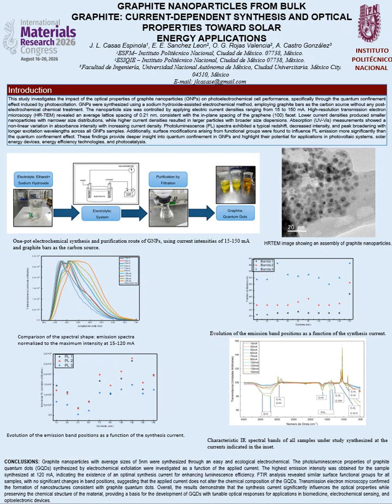In particular, the increase in nanoparticle size up to 6.80 nanometers at 78 milliamperes reveals that at high currents, rapid graphite erosion and possible coalescence or aggregation processes between nanoparticles predominated. This indicates that the current applied in the electrochemical exfoliation of graphite plays a fundamental role in the size of GNPs and is a determining parameter for nanoparticle size control during the electrochemical exfoliation of graphite in a medium composed of NaOH and citric acid.